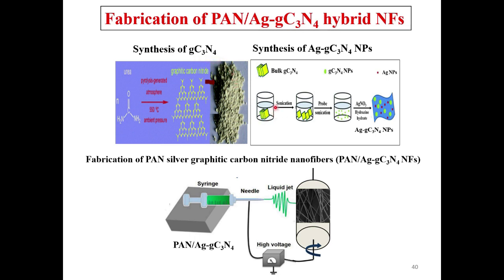We prepare the solution of bulk GC3N4, sonicate it, and disperse it into the solution uniformly with the help of the ultrasonic probe. We prepare the solution of silver nitrate and mix both solutions. Separately, we can synthesize silver nanoparticles with the help of AgNO3, which gives Ag+ and NO3-. Then reduction takes place, Ag+ converted into Ag0. We stabilize that silver nanoparticle for 24 hours, and once stabilized, we mix both solutions and sonicate again, and there is a formation of AgGC3N4 nanoparticles.